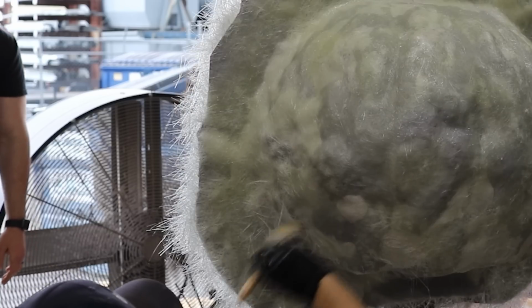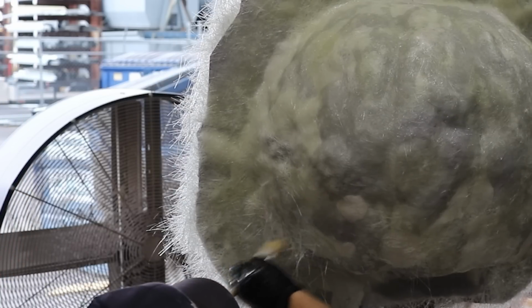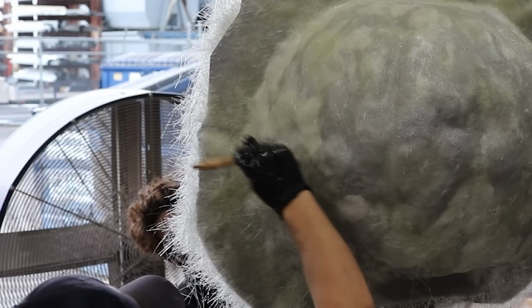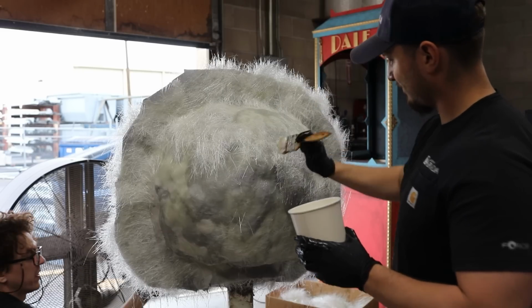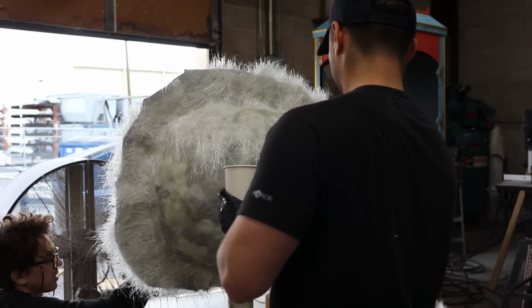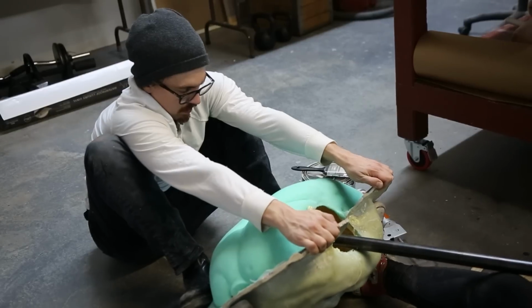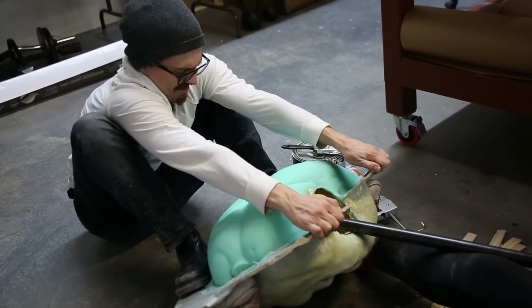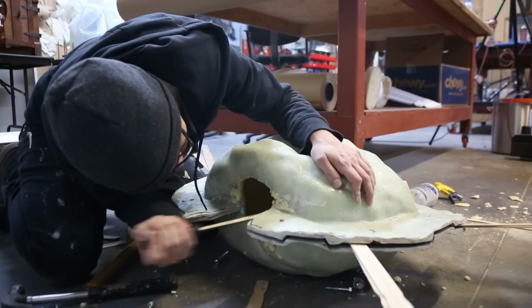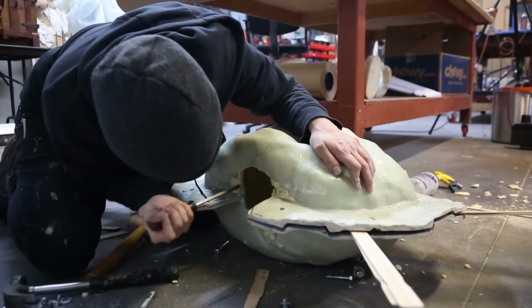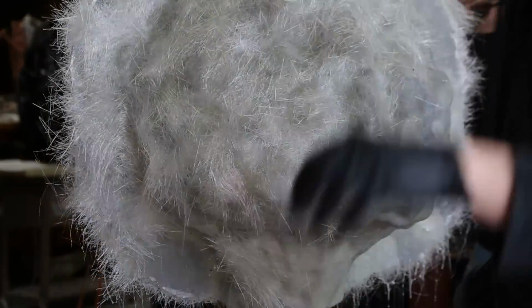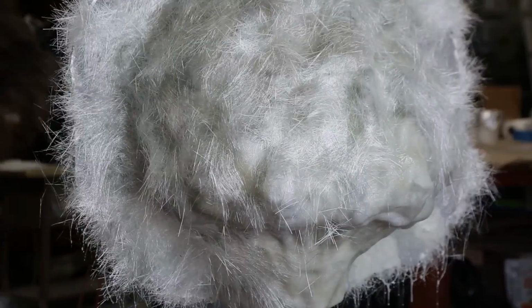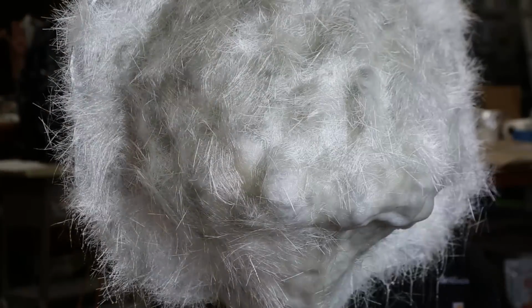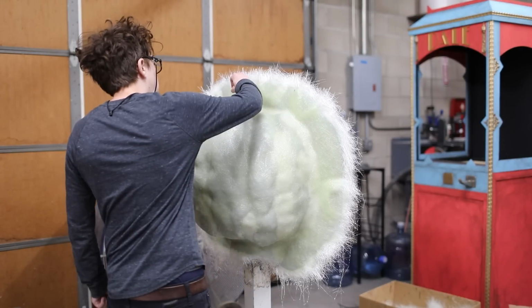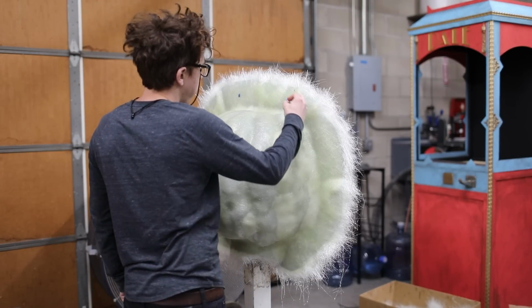Normally for a mold, we do 7 layers, 8 layers, 6 layers. I've done 4 layers, that's a little thin. It also depends on how thick your fiberglass is. Glass is sold in different thicknesses. You want a mold that's about 1/4 of an inch thick, maybe a little less, to give you that strength, to give you something to hold on to. You know it's not gonna crack or flex when you try to remove it from the mold or when you're struggling to open it. So we build up our layers of glass, and then once we build up 6, 7 layers, we're done. We let that sit overnight, we let the chemicals react, and in the morning, it's as hard as a rock. And we have our finished fiberglass mold.